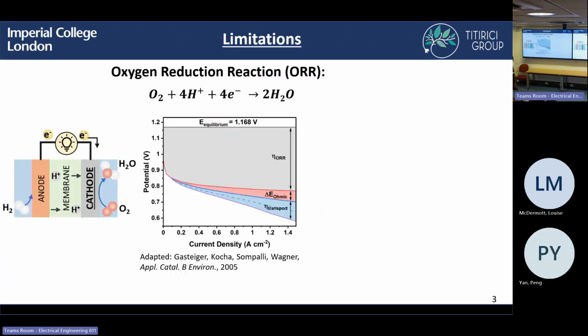The problem with these fuel cells is mainly due to the oxygen reduction reaction. This is where you're converting your oxygen into water. And if you look at your potential versus current density curve, you can see that most of the losses, so this is an overpotential, which is the same as a loss, you see that most of it is coming from the oxygen reduction reaction when you break out the different components of the fuel cell. And so this is really what the focus has been in terms of trying to advance fuel cell technology.